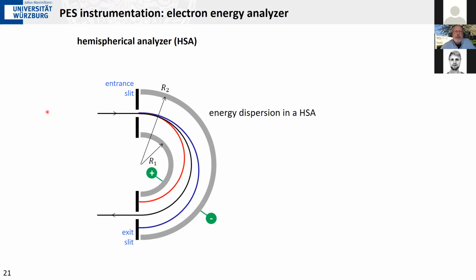Now, when you get the photoelectrons from your sample, you focus them onto an entrance slit. So you have a little slit here before the electrons enter this concentric hemispherical analyzer. You have, if you will, a point source, but the electrons will have different energies. And depending on their energy, they will either go on a path that will bring them to the exact opposite position on the other side of the hemisphere, if they have traveled by angle pi, 180 degrees. And if they do that, they are exactly on the so-called pass energy. Electrons that are lower than that in energy will be attracted by the positively charged inner hemisphere and will reach a position which is away from an exit slit.